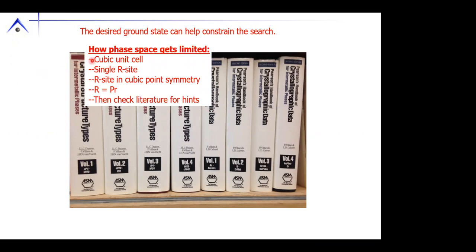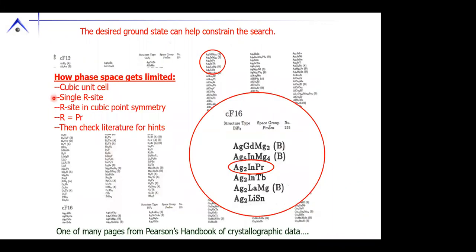I want to have a cubic unit cell with a single rare earth site, with that rare earth site in a cubic point symmetry, and then I want the rare earth to be praseodymium, okay? If I can make it through that cascade, I can then check the literature for hints, okay? So if we go through this, I first look at cubic unit cells, single rare earth, make sure the rare earth is in the cubic point symmetry.